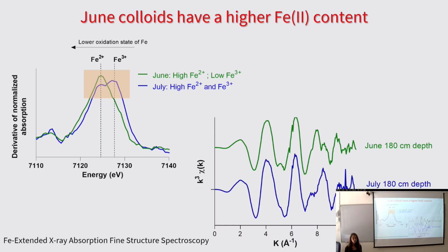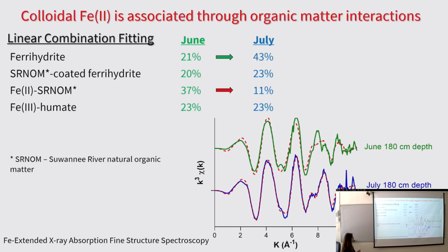So we know that the iron 3 is mostly, or most likely, ferrihydrite, but we don't know about the iron 2. So we employed some more linear combination fitting on these samples. You can see the results of that fitting here in the red dashed lines. The July fitting is a really good fit. The June fit still needs to be improved a bit more, and we're working on that. But despite this, these results are satisfactory to learn about the differences and the trends between these two samples. So the fitting showed that we had main species of iron: ferrihydrite coated with organic matter, iron 2 complex with organic matter, and iron 3 complex with organic matter.